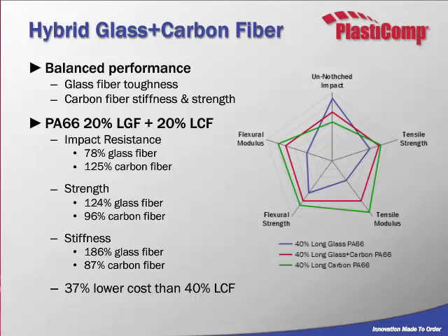Now this chart shows the differences between the hybrid materials and some of our more typical carbon fiber material. If you look at the 40% product, all carbon, you're going to get some advantages in stiffness and strength. But the glass carbon hybrid does push out and fill in the gap, pushes out beyond what a glass-only product could do, and gets very close to the performance levels of a 40% carbon product, but the cost is significantly reduced. So that's the advantage. And as always, there's trade-offs. If it's impact performance only you're looking for, then an all-glass product is probably the right choice. If it's stiffness and price is not as important, then of course the carbon fiber only is probably the right choice. However, if you need a balance, then that's where these hybrid products could come in.